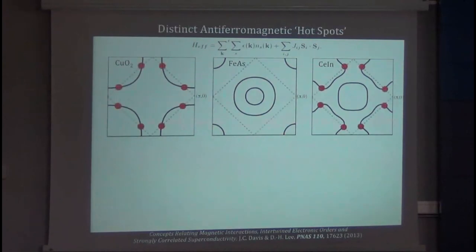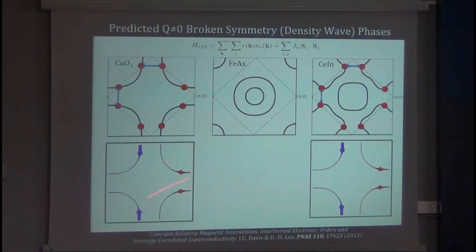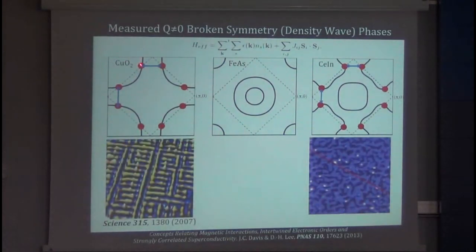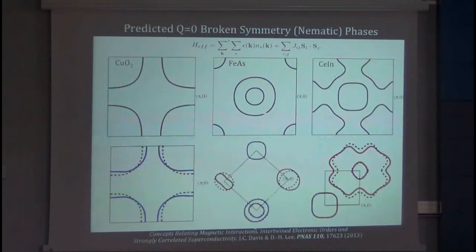Really excellent agreement. Furthermore, and I'm coming to the end of the talk now, so don't panic. Furthermore, the impact of these zone crossings can be used to predict which density wave orders should exist in each compound. One would predict that a charge density wave with this scattering wave vector should exist in the cuprates, and that's exactly what exists in the cuprates. One would predict that no charge density wave exists in the pnictides because the antiferromagnetic Brillouin zone does not cross the Fermi surface. And we're not quite sure, there should be a weak charge density wave in the heavy fermions.